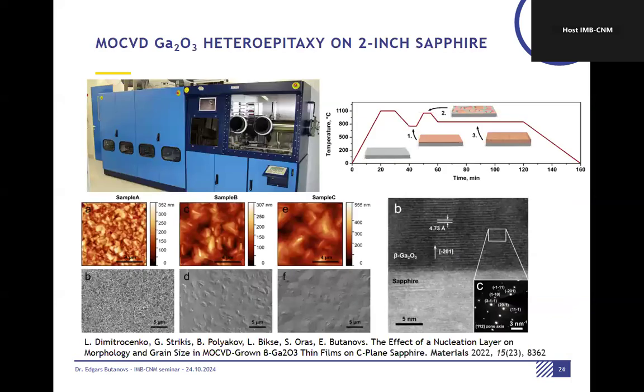Then we'll move to MOCVD. So this is kind of interesting. We can do epitaxy on 2-inch substrates. So that's already something more interesting from the device perspective. For now, we have worked only on sapphire substrates. So it's heteroepitaxy, and unfortunately, beta phase gallium oxide does not match very well with this aluminum oxide. So there are still quite a lot of defects.